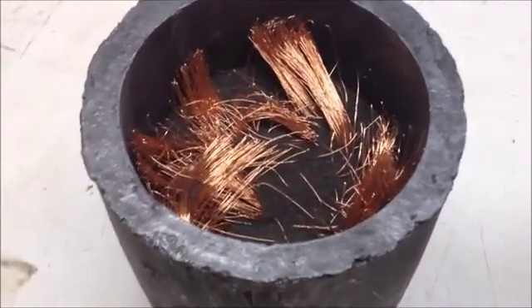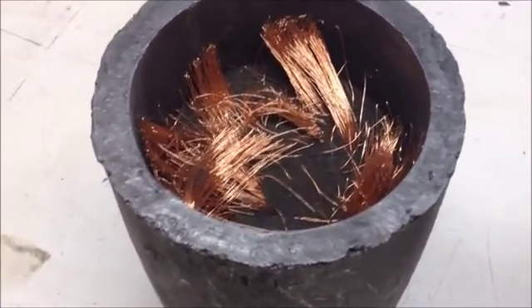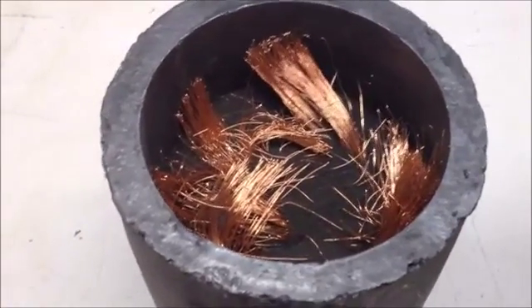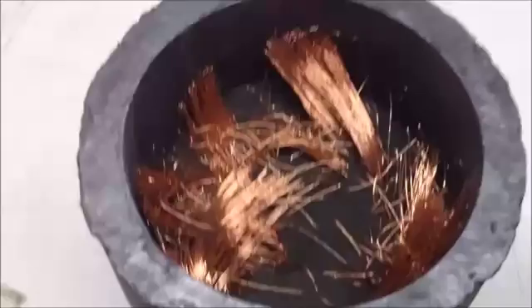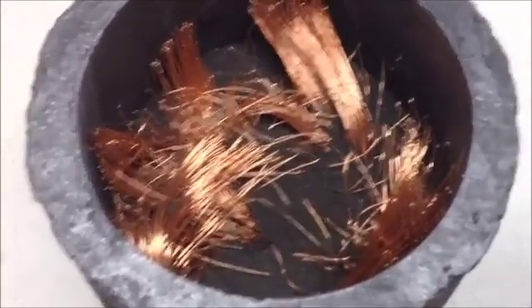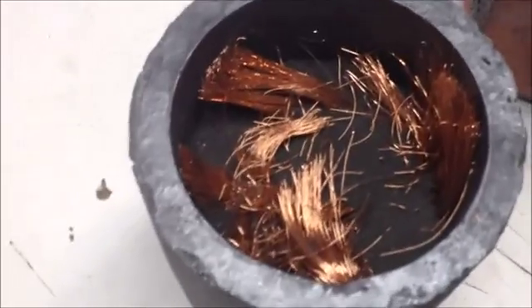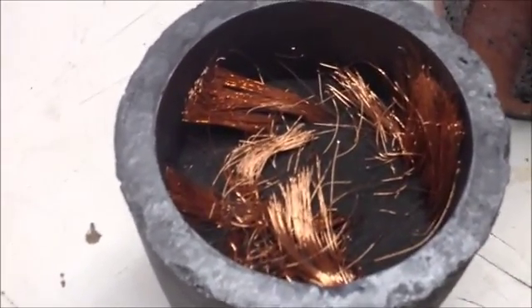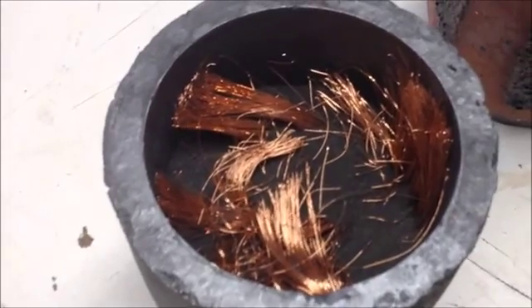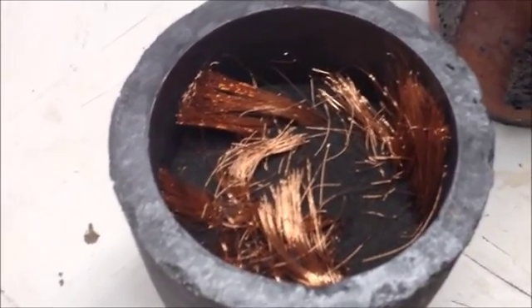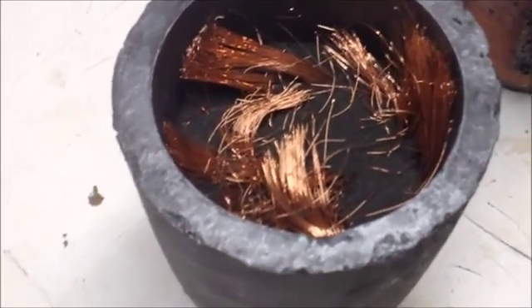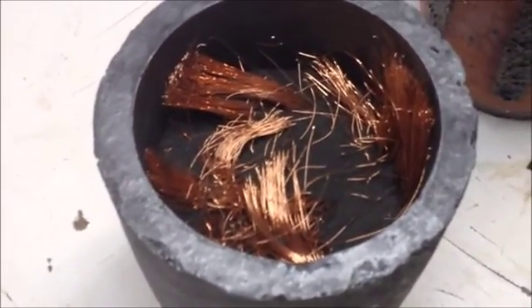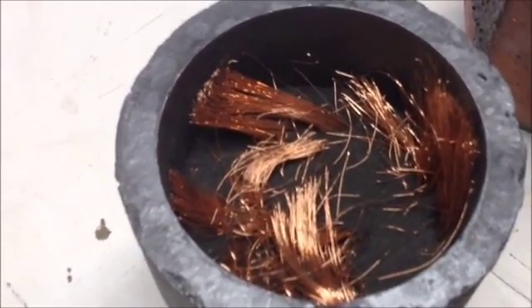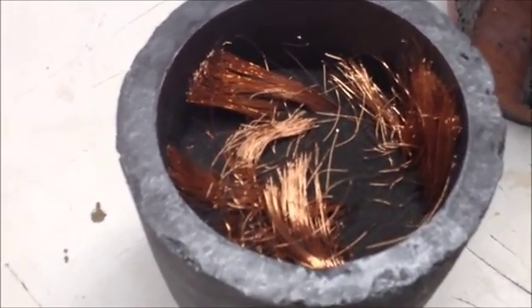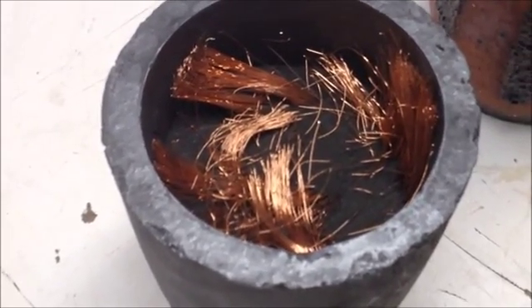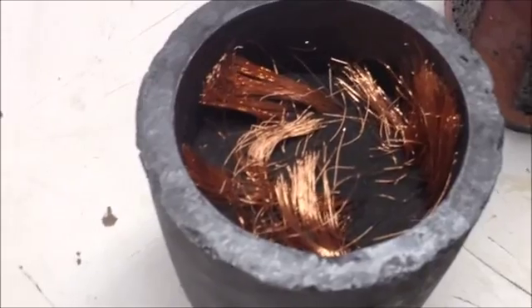I took 1 cup of the high-grade number 1 and number 2 and mixed it with 2.5 cups of Chapman flux, and I added about a pound of fine copper wire to the mix as a collector metal, because I found that if you don't have enough metal in the charge, when you pour your material in your conical mold, you don't get any button at the bottom. It all stays suspended in the slag. So you need a collector metal to filter down through the material and capture the gold and other precious metals, silver, and bring it down to the bottom in a button, or it actually turns out to be a little pyramid. So I use copper.